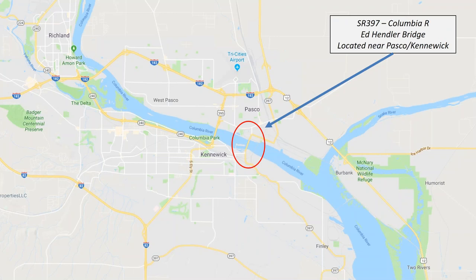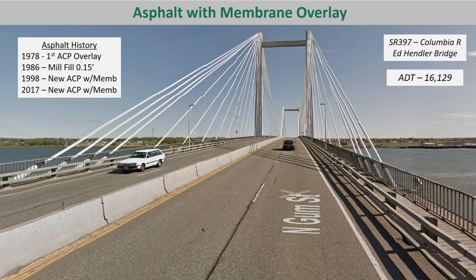Here's a location map. It was, more or less, a city street that was turned into a state highway. The main state highway is 395, and so this 397 doesn't have a lot of traffic. But here it shows kind of a history of what we did on the bridge. Original asphalt overlay, and then we did a mill and fill, which means taking off a portion of the asphalt membrane. And then in 1998 and 2017 did asphalt with new membrane.